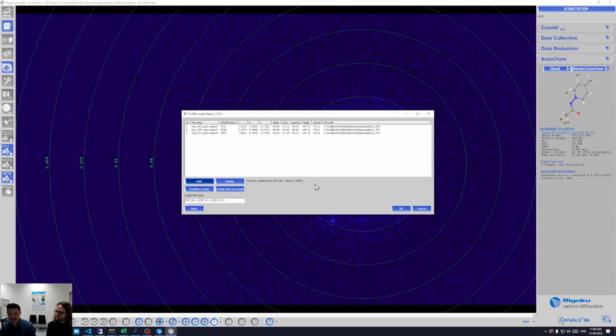Typically it is like 3 to 4. Okay. Again, it depends on if it's a centrosymmetric space group or non-centrosymmetric space group. Yeah, and then it also depends on the orientation of the crystal or grain itself on the grid. So sometimes you suffer from preferred orientation, especially for plate-like crystal morphologies, where you will often have to look a bit for crystals that are hanging in space a bit weirdly